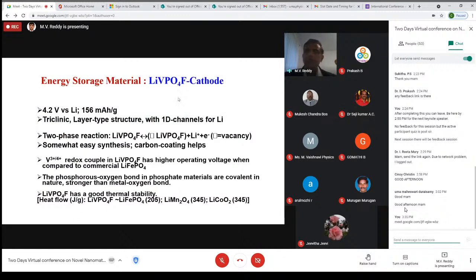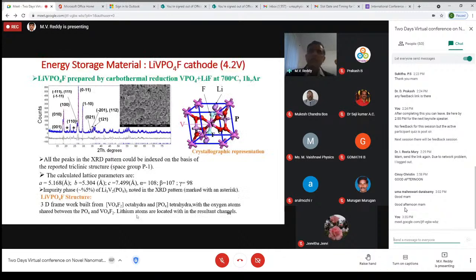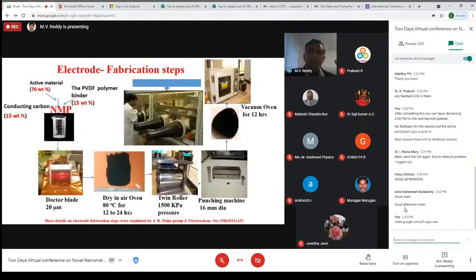One example is the lithium vanadium fluorophosphate cathode. Again, it has nearly 4 volts potential and reasonably good thermal stability, etc. This sample, since I don't have time, was prepared by the previous carbothermal reduction method, and characterized by using XRD.